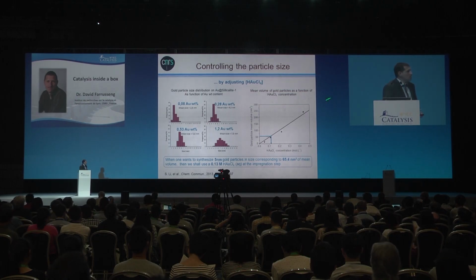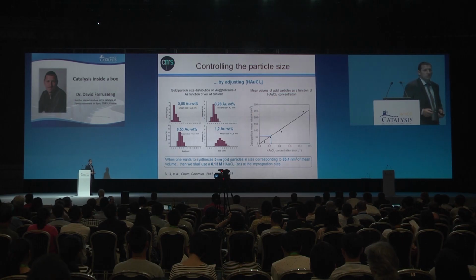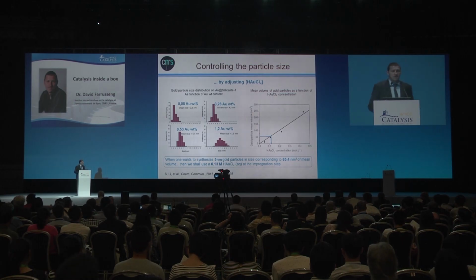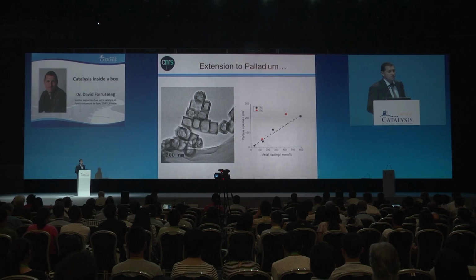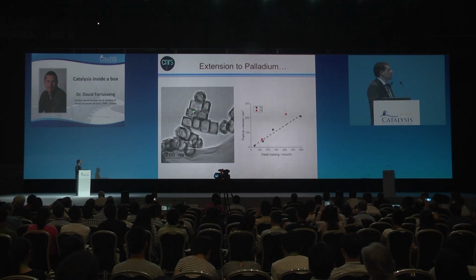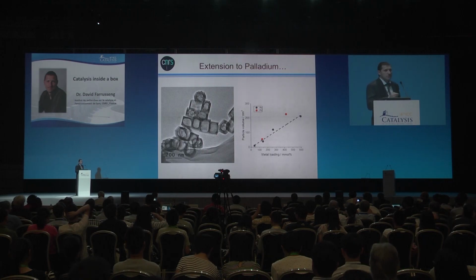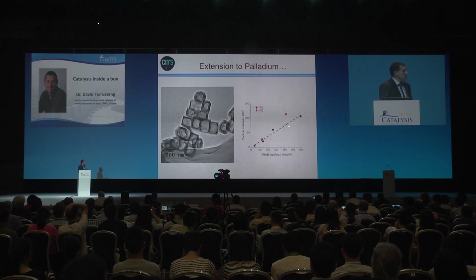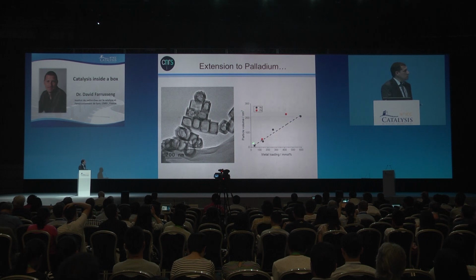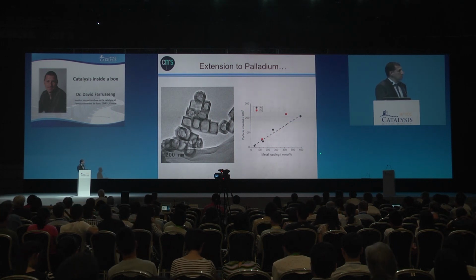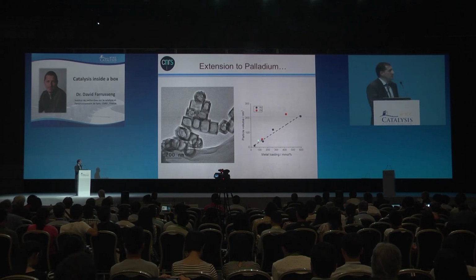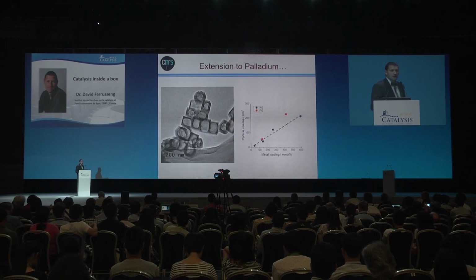Then if it works for gold, it should also work for other metals. And we did it for palladium, for example. In each cavity here, you can find one single particle of very controlled size. We plot here in black the gold particle volume as a function of the metal loading. And in red, you can see the palladium. So this is, I think, a general rule.